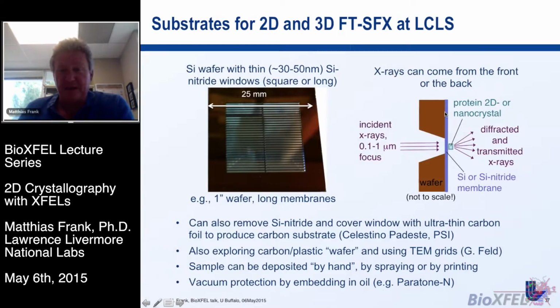Here on the right is the principle shown again. So we have a silicon wafer. It's a cross section with a thin layer of silicon nitride, and that's usually produced before you etch out the silicon from behind the silicon nitride, and remaining is the silicon nitride membrane. And you can shoot X-rays onto that either from the front or the back, and then if a sample is present, you will get diffraction that you then can measure with the detector.